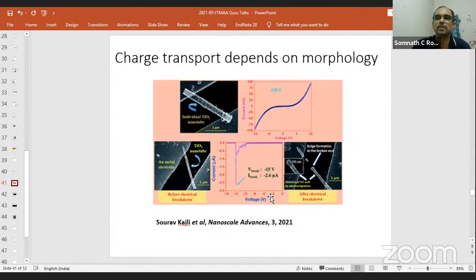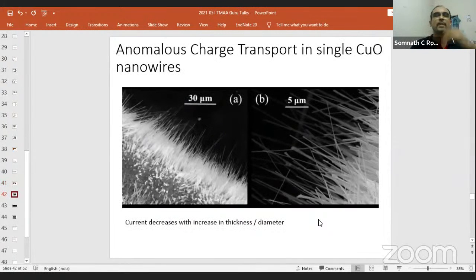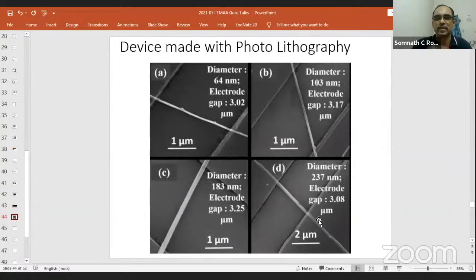We wanted to look at how a single nanotube or single nanowire behaves. So we carried out charge transport characteristics on a single nanotube, as you can see here, placed onto a photolithographically patterned electrode. We have also done detailed empirical modeling of that. We have also shown up to what current it sustains before it breaks, and what voltage it sustains before it breaks. So that if someone is interested in future in making a single TiO2 nanotube device, he or she will have an idea from our work of what kind of nanotube can sustain what voltage limit, compliance limit or current limit. So this work is on a more fundamental scale, but very interesting work. Similarly, we have taken up these copper oxide nanowires also, and done similar measurements, and we have seen another particular thing that I will show you.